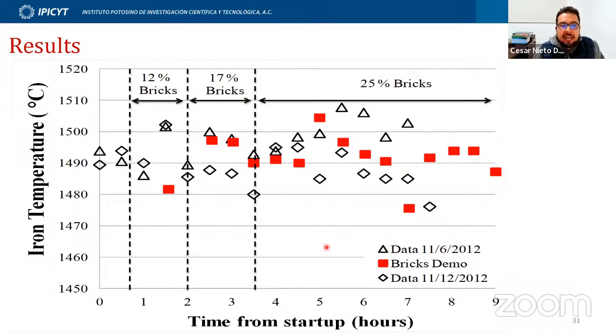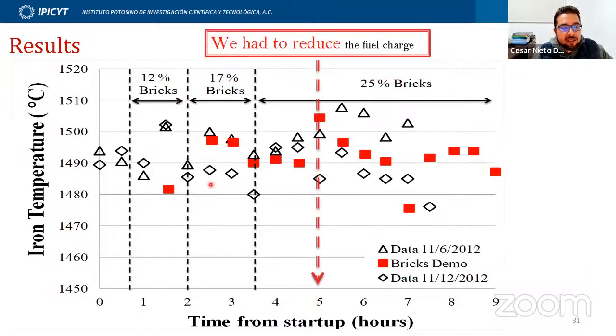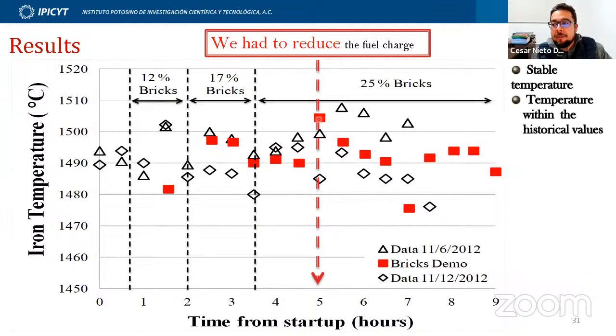The open symbols are just regular day operations when they are using 100% coke. And you can see in these lines the replacement of the coke by bricks. You can see in these operations that we have a very stable temperature around 1490 °C. Even at this point, we had to cut the carbon source, or the fuel, because the temperature was going very, very high. And when you are melting iron, you want a very constant temperature, because if it goes very high, then you have problems in the metal casting. But anyway, these were very good results, a very stable temperature, and also the temperature was within the historical range, like when they were using 100% coke.